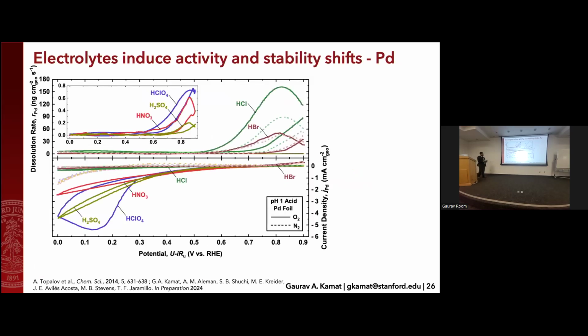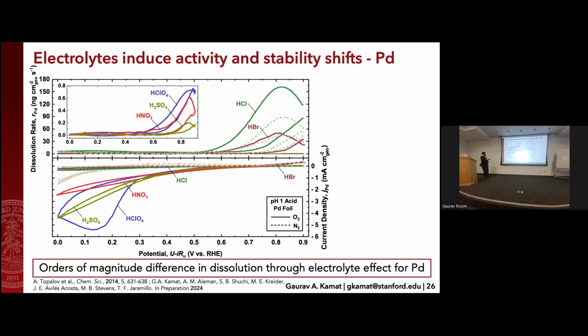So here's what some of this data looks like. This is a palladium foil, and this was done for 5 different acids, all pH 1. And what you can see is that for perchloric, sulfuric, and nitric, all of these cyclic voltammograms are higher in onset. But then you have hydrobromic and hydrochloric that don't really do much oxygen reduction in these settings. Now, on top of that is stacked the dissolution rate. And the units of this dissolution rate are nanograms per centimeter squared per second. 10 to the minus 9 grams. This is a very, very tiny dissolution rate. And in the case of hydrochloric and hydrobromic, it's on the order of hundreds of nanograms per centimeter squared per second. And in the case of nitric, sulfuric, and perchloric, we do have differences, but you see they're all less than 1. So you have huge order of magnitude differences in how this electrolyte effect changes dissolution on a single metal.